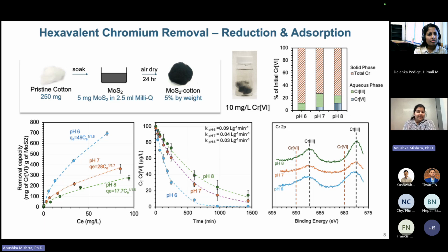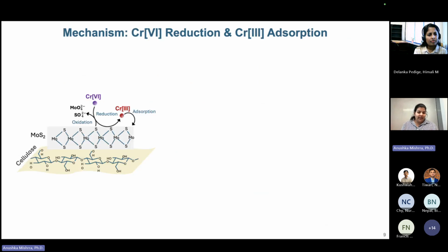We also did some XPS characterization for the material to see what phase of the chromium existed on the cotton after the reaction took place. We saw that for all the pH levels, chromium-3 was our dominant phase, confirming that chromium-6 was in fact turning to chromium-3 on the surface of the MOS2 cotton.